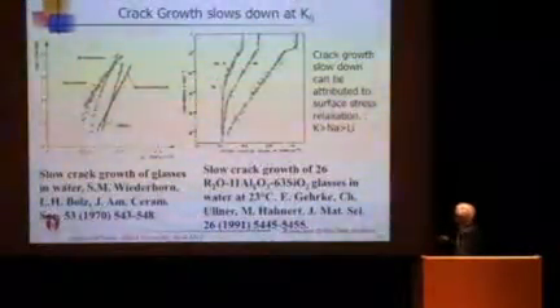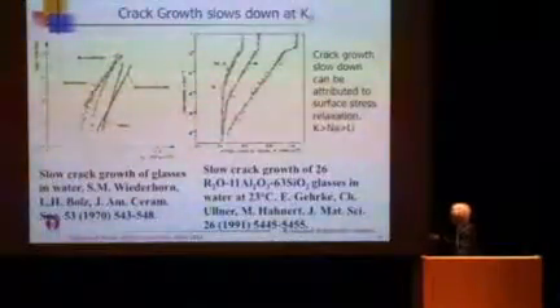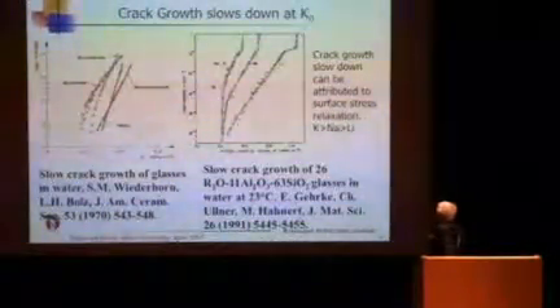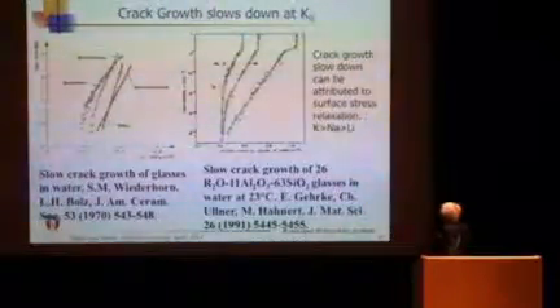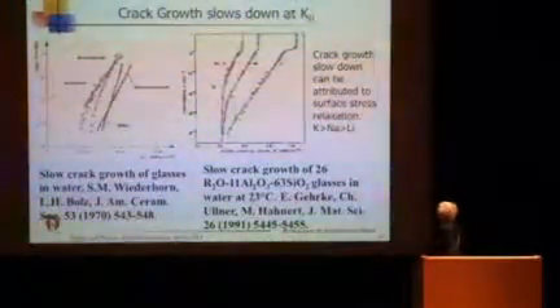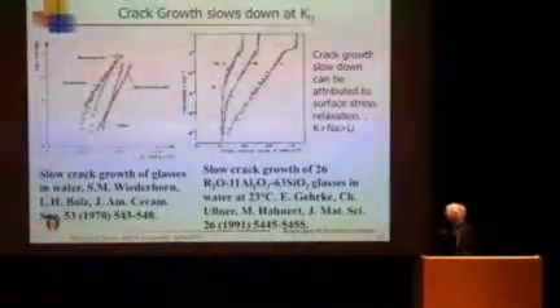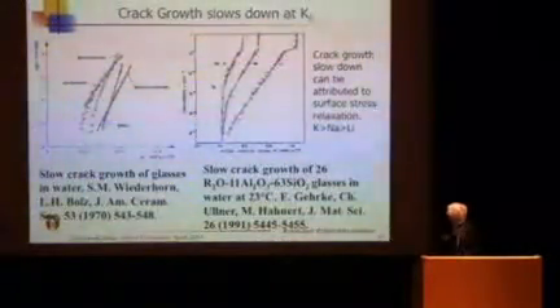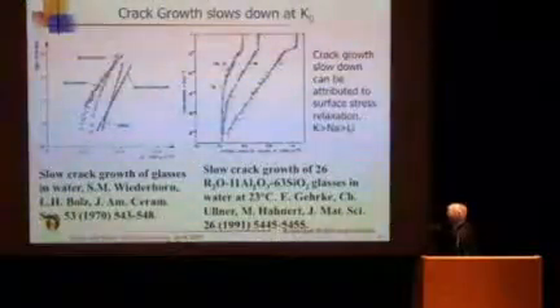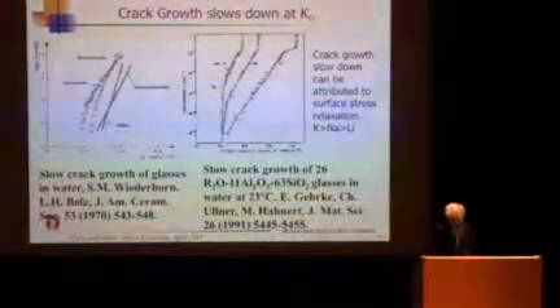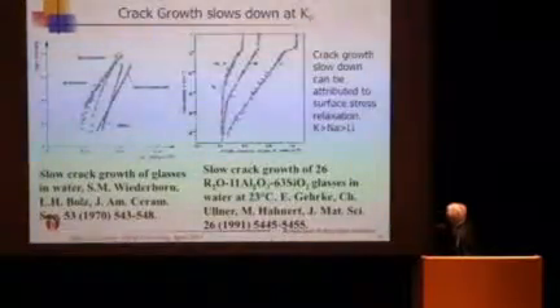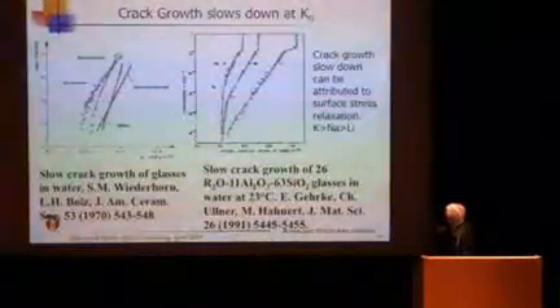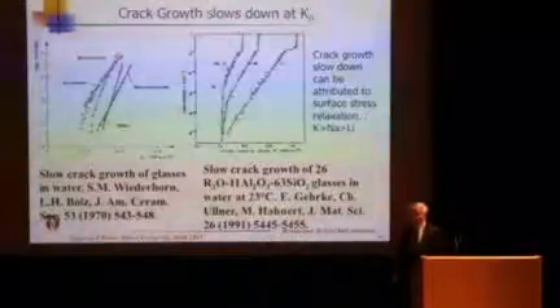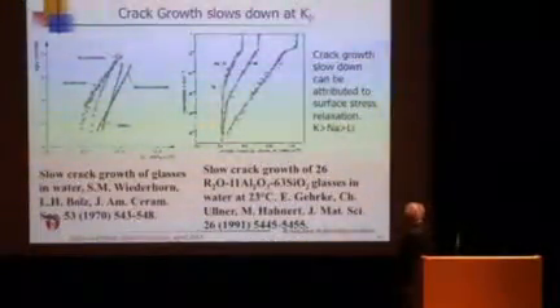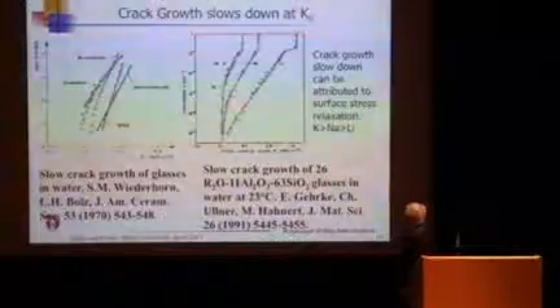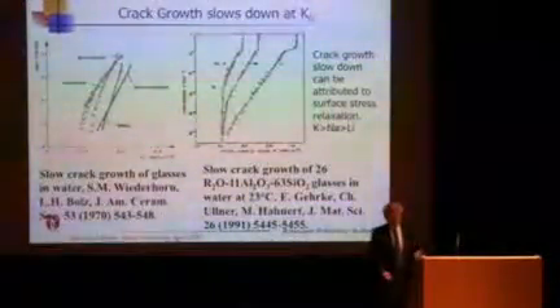In this case, it was done in water. I believe this one is also water. So water is causing this. If you do air, that happens slightly slower but with a similar trend. What is interesting is that the crack growth, logarithmic to stress intensity, is normally linear. But if you go down, down, down, it starts to drop faster. So somewhere around here corresponds to the fatigue limit. Below this stress intensity, crack growth wouldn't happen. So this must be caused by surface stress relaxation.